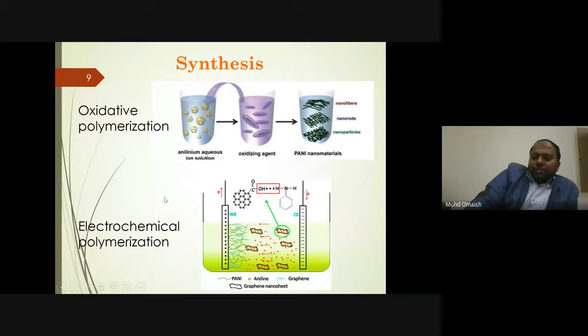But the most commonly adopted route is oxidative polymerization, because of its ease, and you can easily polymerize aniline, pyrrole, thiophene, by using oxidants like ammonium persulfate, potassium persulfate, ferric chloride, and others.